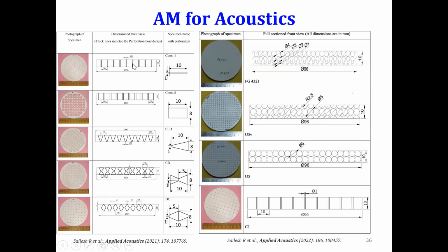We use the same 3D printers for printing the panels for acoustics, which absorb the sound wave very efficiently. These panels are biodegradable and very lightweight with micro perforation, which is possible only in a 3D printer, because we can have such straight holes drilled using a micro machining technique, but definitely not this structure, neither this nor this. Forget about the spherical pores. So we also did spherical pore micro perforated panels and the graded versions of that. So the sphere diameter increases slowly from one end to the other end.